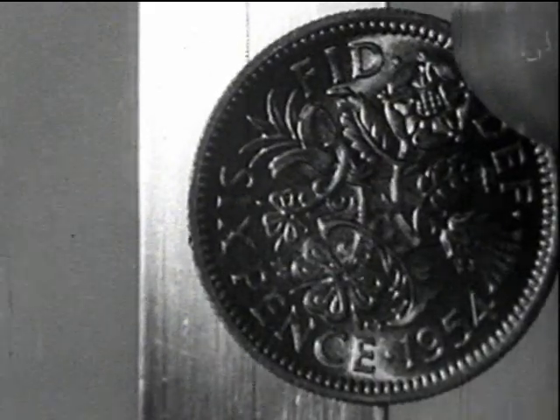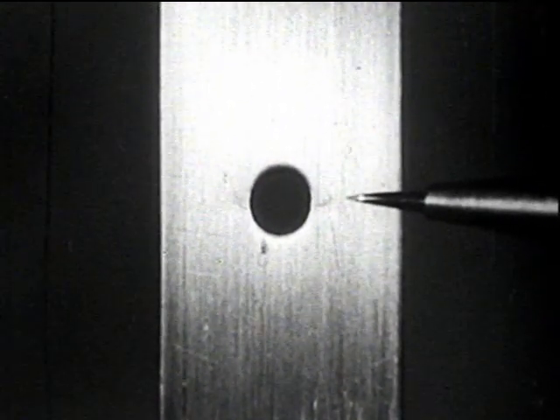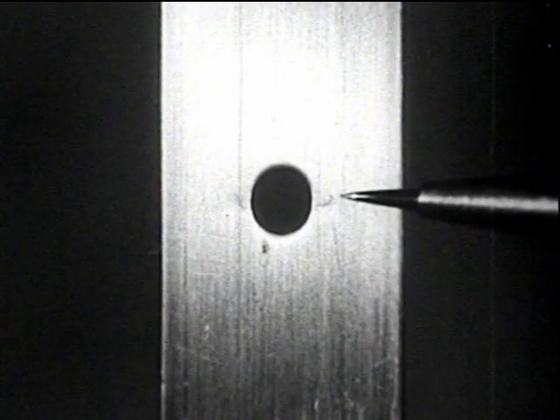A series of laboratory tests were made to study fatigue stresses around a rivet hole, and specimens of aluminium alloy sheet, similar to those used in the Comet fuselage, were stressed in a fatigue testing machine 2,000 times per minute from 0 to 40,000 pounds per square inch. Under these stressing conditions, the specimen fractures in about six minutes.